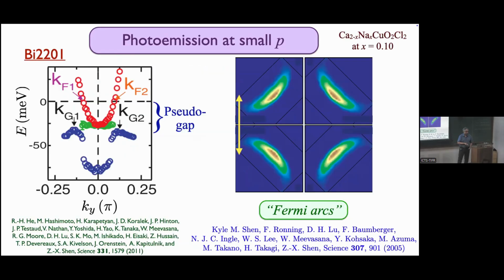But when you lower the temperature or lower the doping, then you get this blue curve. And this doesn't cross zero at all. And it actually has a minimum gap here at some finite wave vector, which is in fact not the same as KF, as this paper emphasized. And that's the electronic pseudogap. It's a clearly formed gap in this region. It's quite large, 30 meV or so. And if you go to exactly (pi, 0), then it's almost 75 meV.